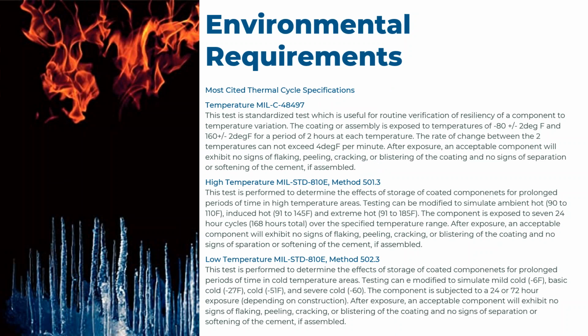Thermal cycling, another important aspect that we have to explore. Thermal cycling is basically, just as it sounds, you're heating up your optic as you use it. You're getting it to a very high temperature, and you're taking it down sub-zero. What you're supposed to model in the film is how is the film going to interact with the heat changes, and are we going to induce stress, create adhesion loss, or ruin the optical performance of the film? Again, there are different modes that we're going to explore here. Some are a lot more aggressive than others.